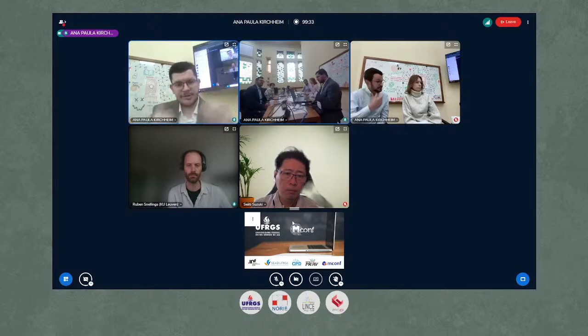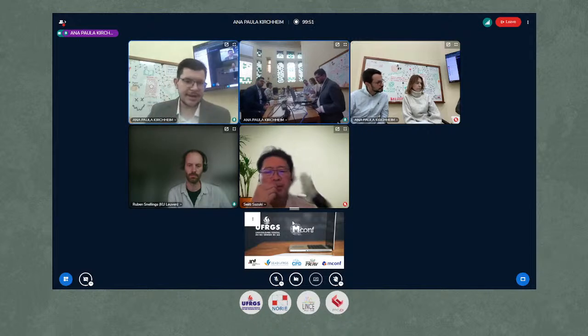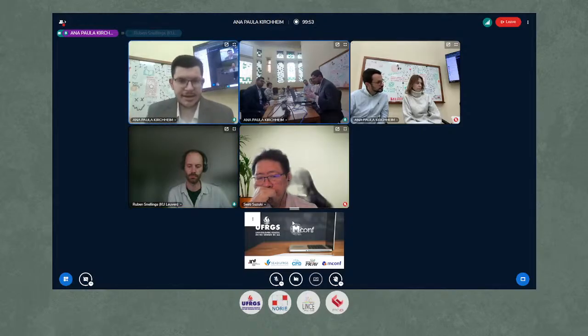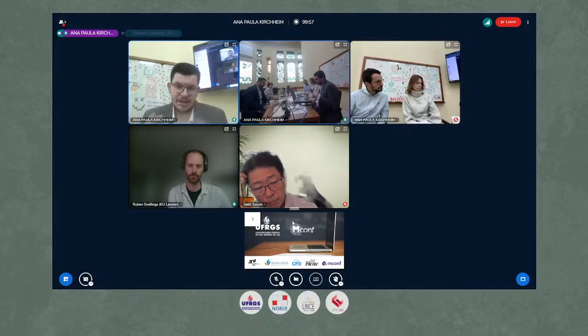So I will redo the analysis with this better data and also check the mass balance calculation, because for me it was also weird, because I think it's a very small C3A dissolution to form so much ettringite and then it's stable. So I will do it again with the better data, better diffractograms, and I will check with mass balance calculation if it makes sense.